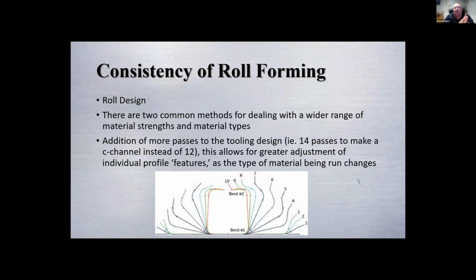Flare can be controlled, but it will never be eliminated. If anybody can eliminate flare, they need to patent it, and they will be a very wealthy person. But here's some of the ways that they do it. On this product here, they're doing a channel, and they're doing it in 10 passes. That's what those numbers mean in the diagram. But as you can see, it's supposed to be up and straight, like on pass 9, it's actually complete. But on 10, they're actually overbending it. And the reason why they're doing that is so when it comes out and it releases, it stays. And that bend number 1 will stay at 90 degrees and give you a nice straight cross section, or a straight leg, to stay within that plus or minus 2-degree tolerance.